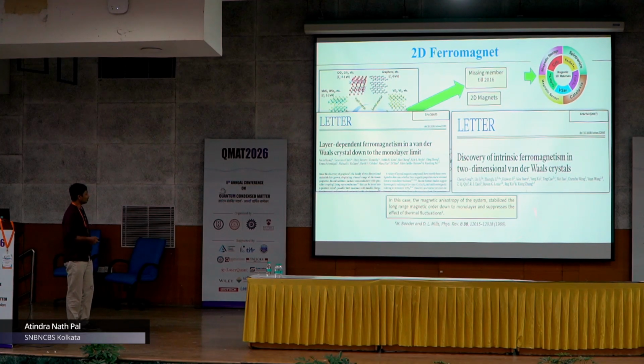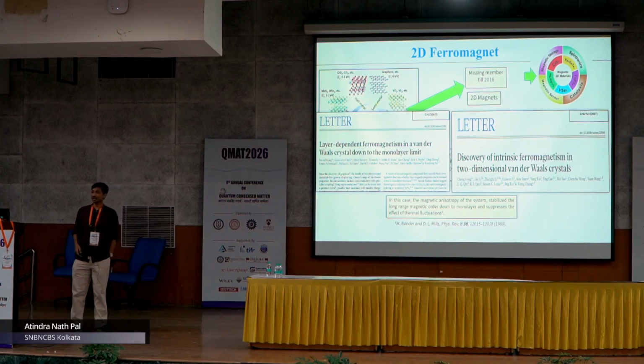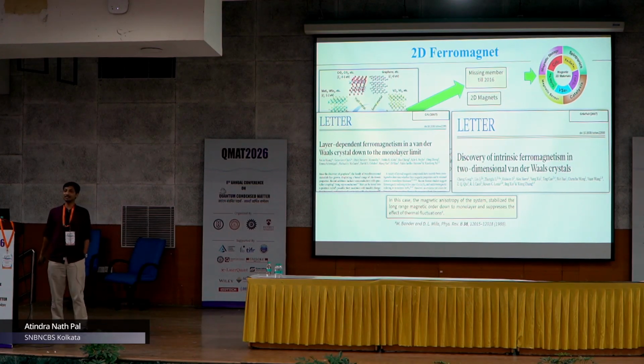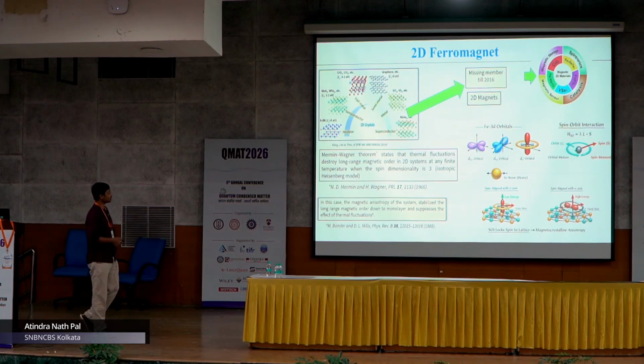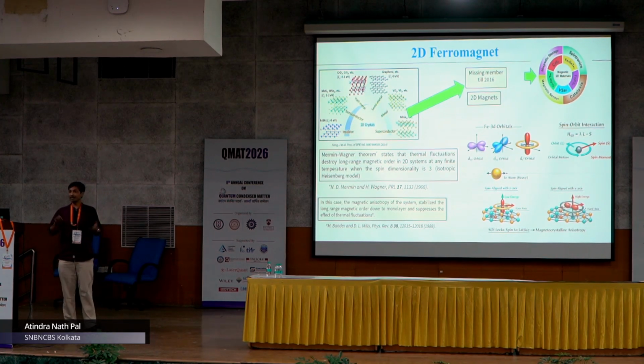The main thing is the magnetocrystalline anisotropy, which stabilizes this magnetic order. In brief, in our system we have iron, which has different orbitals that are degenerate, but in a crystal you have a particular crystallographic symmetry and also spin orbit coupling, a term like L dot S, which couples the crystal with the spin.